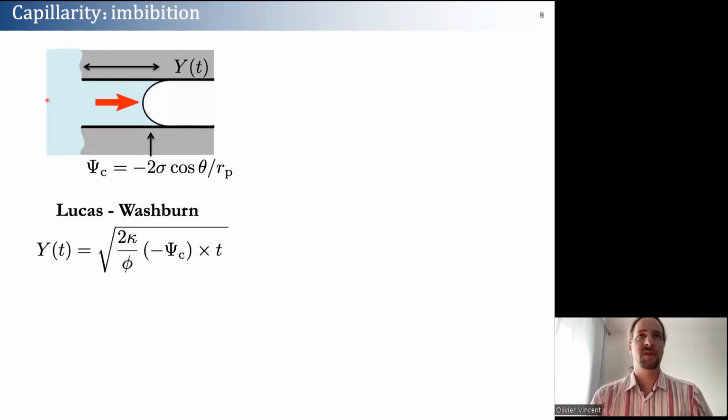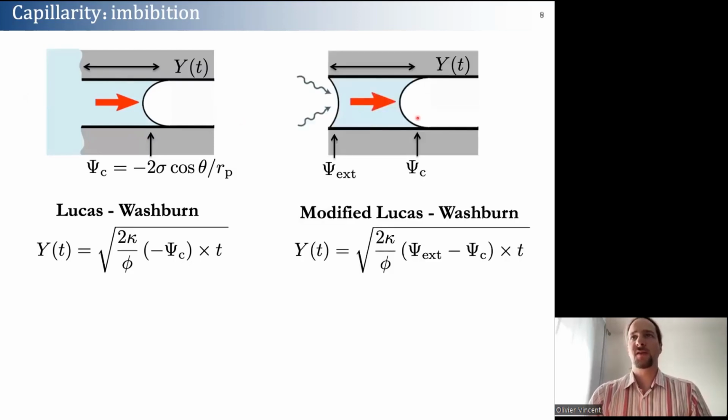Here we have a slightly different system where we have a meniscus from the condensate that's trying to invade the system, but also there's another meniscus at the edge between the liquid and the outside vapor phase that kind of resists the invasion. And of course, the speed at which the liquid will invade the system depends a lot on the competition between these two menisci. This meniscus is just driven by the intrinsic capillary pressure of the pore, but again, for this meniscus, its curvature is driven by the Kelvin equation, and it's fixed by the humidity outside from the equations we saw before.